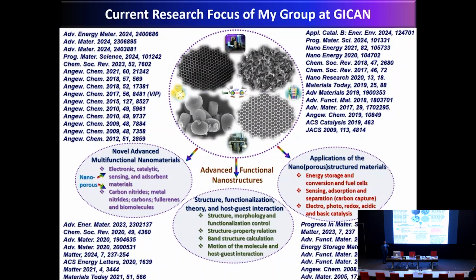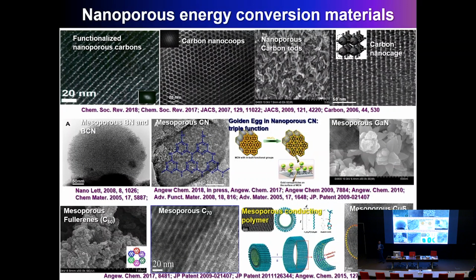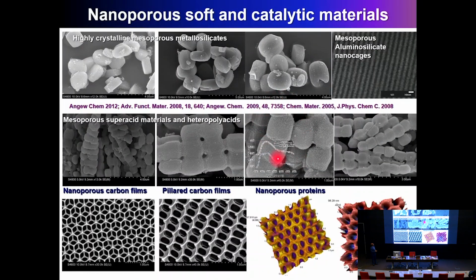There are several new materials that we have discovered, and some of them are shown here. The carbon nanocage and carbon nanocoops. They have a three-dimensional cage-type porous structure with a surface area in the range of 2,000 to 4,500 square meters per gram. And many people have been using this material for energy storage applications. And we are the first ones who introduced highly ordered nanoporosity in carbon nitride, boronated and boron carbonated materials, even in fullerene nanostructures with the C₆₀ and C₇₀. And several conducting polymers and semiconducting nanostructures, even soft materials and mesoporous superacidic material with a very, very high Brønsted acidity, and we can use it for cracking reactions.